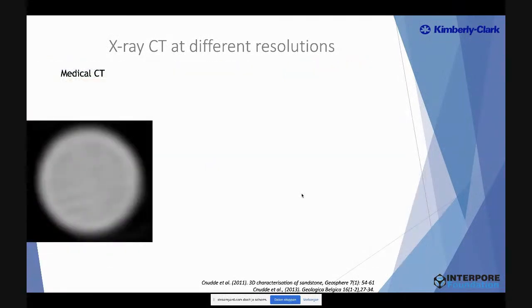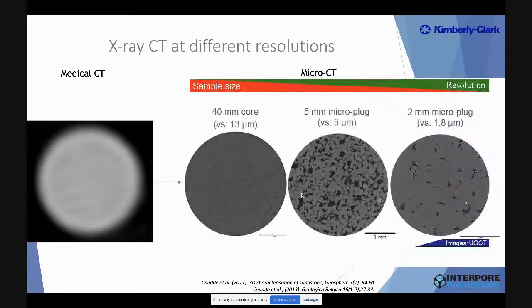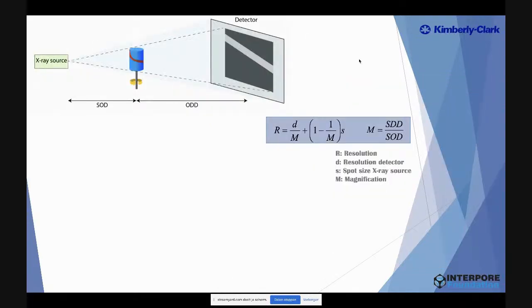But of course, if you want to go for pore-scale processes, this resolution is not high enough. So typically we go to micro-CT, where we take samples which have a smaller diameter, and by going to smaller diameters, we gain in resolution, and we can see the individual grains and the individual pores inside our rock. And to explain the principle of resolution, I have here a scheme where I show all the important features that determine the resolution of a system.